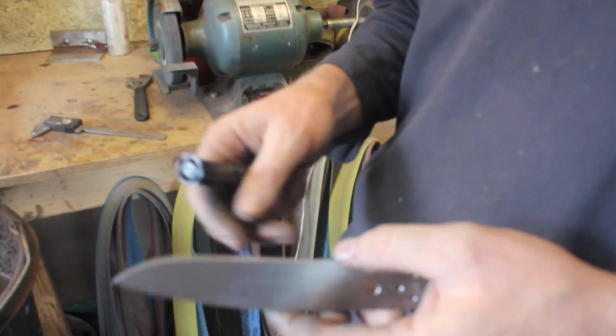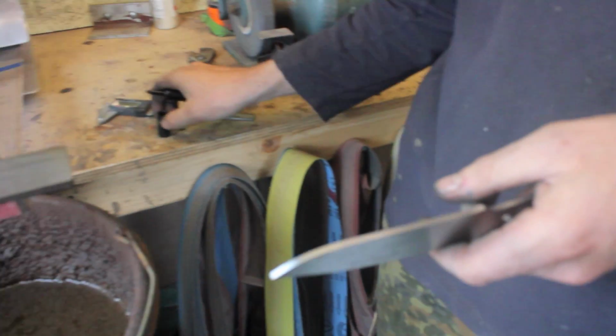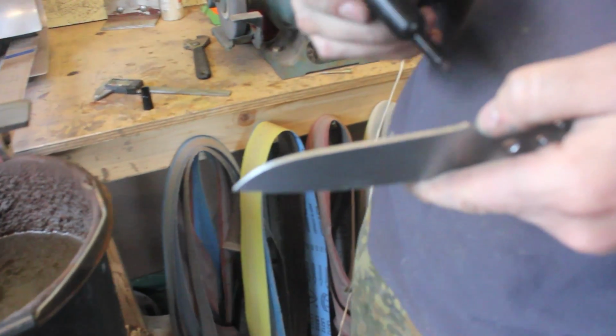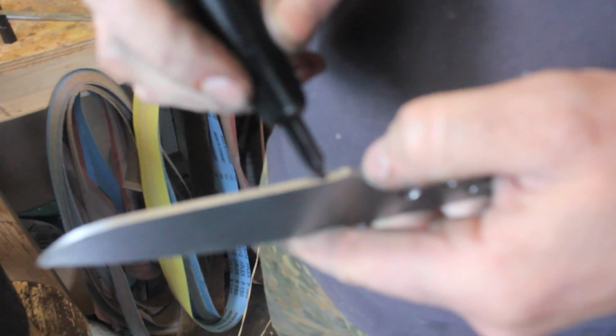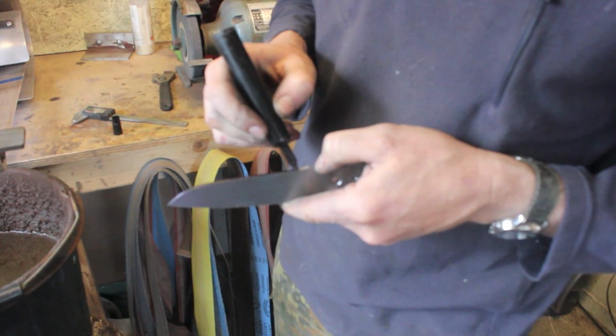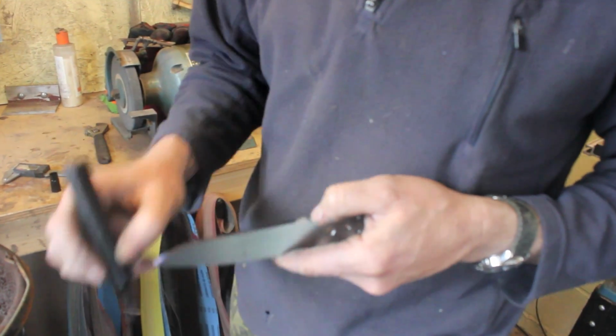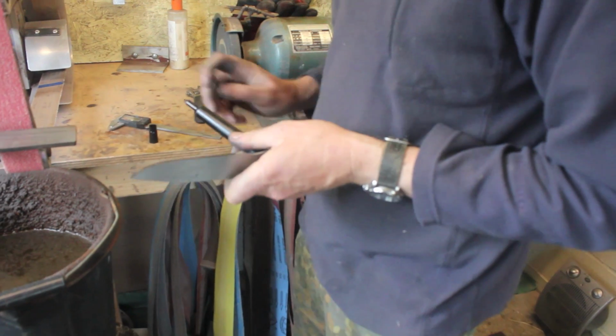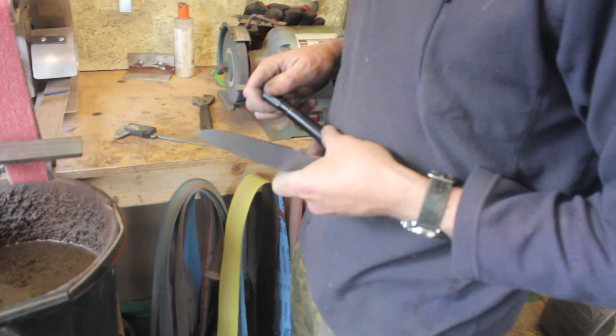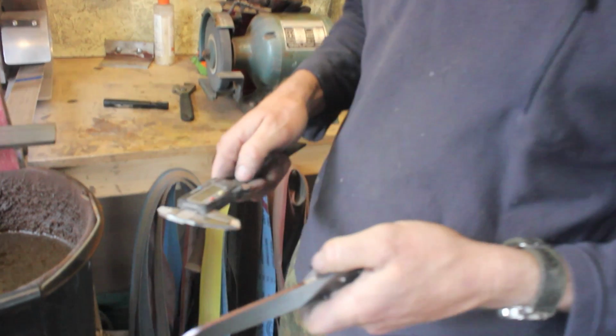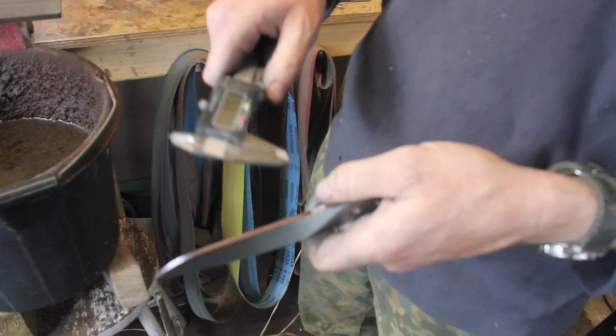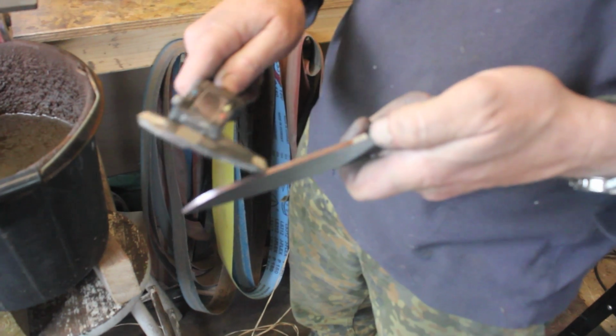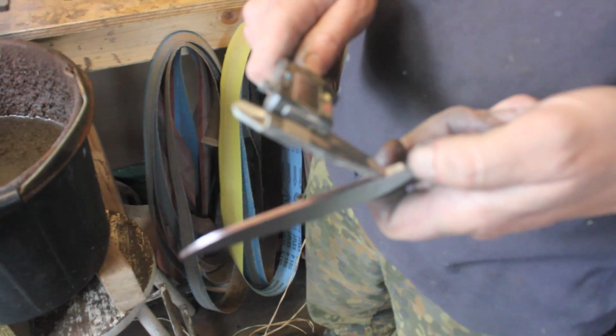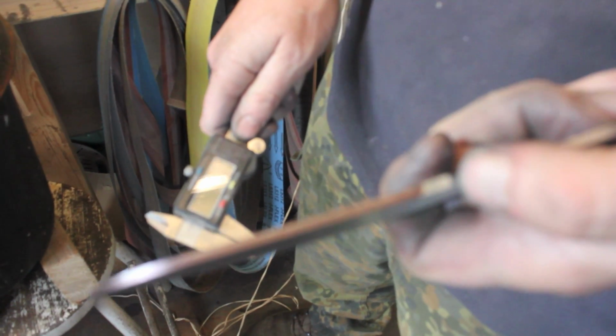I'm just about to apply the primary pre-heat treat bevel onto this knife. What I do, I call it inking up. I don't know what the name for it really is, but I call it inking up. So basically I just get an indelible marker and ink up where the cutting edge is going to be. And then using a set of vernier gauges, set them to a certain measurement depending on the thickness, and basically just scribe a line down one side, turn it over.